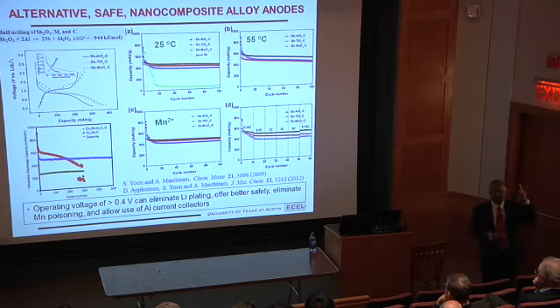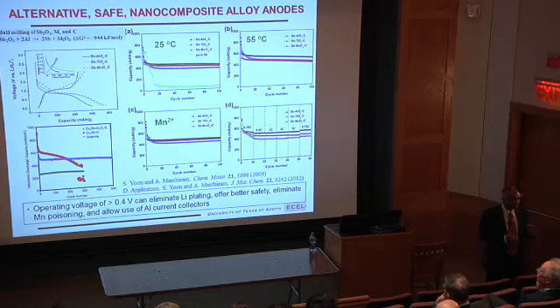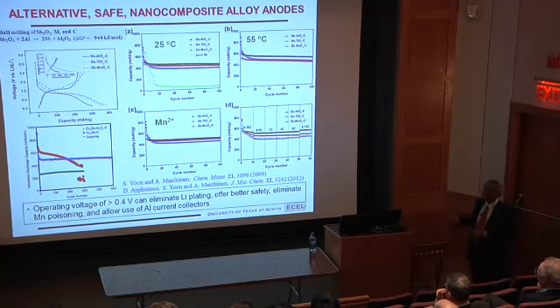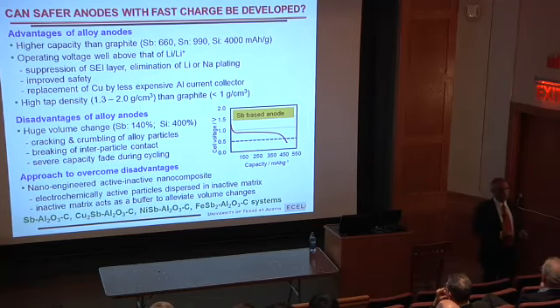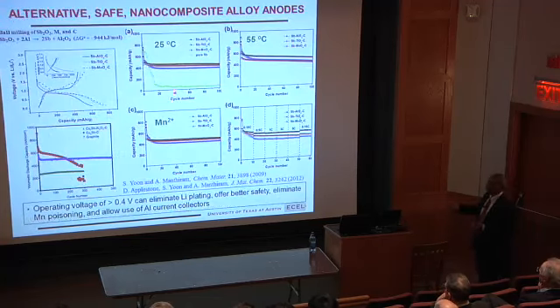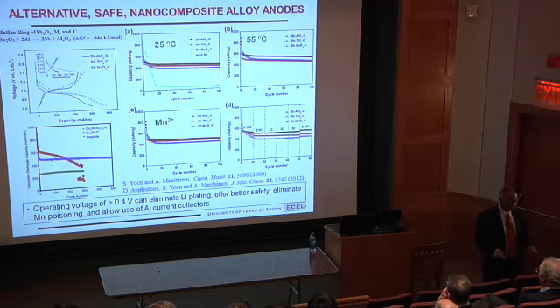Our operating voltage is higher, therefore I will lose some energy. But tap density is high, yes. So how much do you sacrifice the specific capacity by adding the extra matrix to it? No, the capacity I'm giving you here, people will cheat. I'm not cheating here. The capacity I'm putting here is for the whole composite, not just antimony. So that's my electrode. I'm considering my aluminum oxide and carbon as active material.